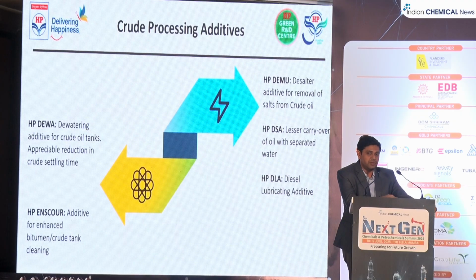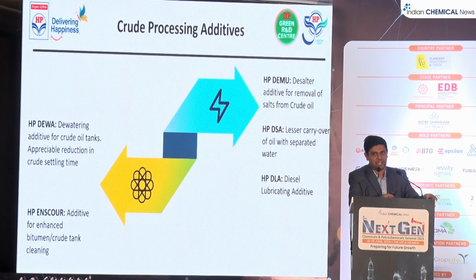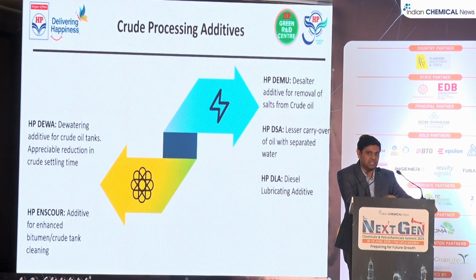HP ENSCOUR is a chemical which basically dissolves the asphaltene residue at the bottom of the crude tank. Generally, crude tank cleaning takes a lot of time. It takes almost 3 to 4 months to clean the tank bottom residue, which is very hard, and manual scavenging and manual scrapping is required. So by addition of this chemical, we can reduce the man days to half, and we are using that in our refinery.